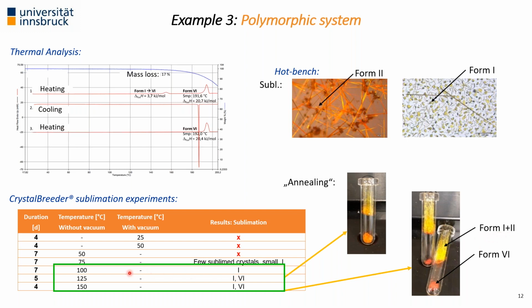2. With this setup at a higher temperature, it was not possible to produce phase pure form 2, mainly because we stayed for too long time at the higher temperatures, not too high. And here you can also see within the crystal breeder, the heating block. Here the temperature was applied, because what we also had with our device, it was tailor-made, that the heating blocks were cut a little bit, that we had a higher temperature gradient. And at the interface here, you see still form 6 is growing, and here the other polymorphs.